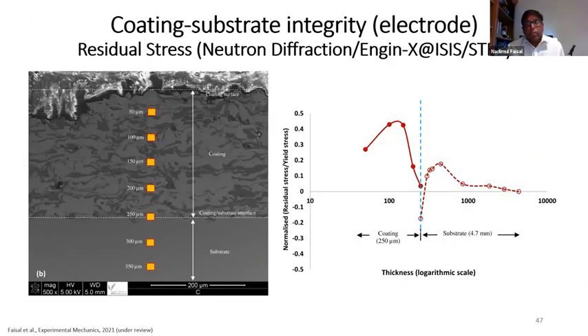Here we did some non-destructive testing where we used the neutron diffraction technique at Rutherford lab. And you can see that this is the interface, and at this interface, there is a huge mismatch of the strain, but this is within the safe limit. These are the normalized residual stress. You will find that through the thickness of the anode layer, the strain change is not one number.